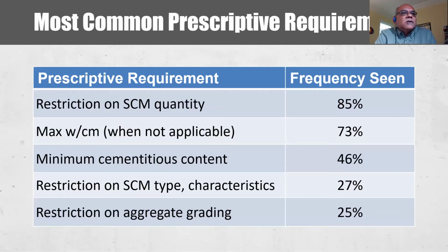85% of the specifications that we reviewed had a maximum limit on the supplementary cementing material content. This tends to be a misuse of the typical clause that you might see in a master spec, where a limit is put on fly ash and slag, a maximum limit, very specifically for members that will have exposure to freezing and thawing type situations with the application of de-icing chemicals. However, that is generally ignored and applied to all concrete in a structure. You very often see a maximum water cement ratio when it may not be necessary for durability. And in many cases, there is a disconnect between the specified maximum water cement ratio and the strength requirement.